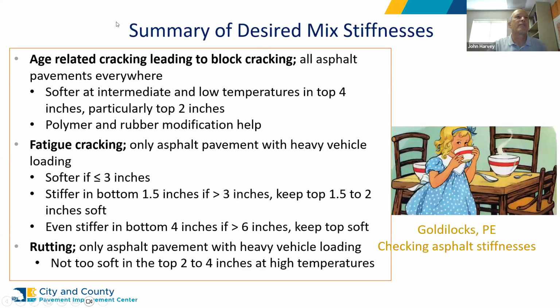So to summarize, desired mix stiffnesses, age-related cracking, which leads to block cracking, all pavements everywhere, all the time. You want to be softer at intermediate and low temperatures in the top 4 inches, particularly the top 2 inches. Just gave a talk yesterday at the Public Works Officers Institute. What that means in the top 2 inches is you want to minimize the amount of wrap in that layer, unless you go to higher levels of wrap, above 15 to 25%. And then there are technologies and approaches where you can keep that softness but still accommodate wrap.